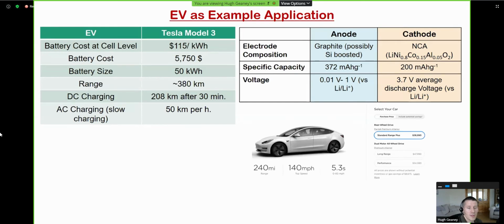If we're talking about just the graphite on its own, the capacity of graphite is about 372 milliamp hours per gram, which essentially is just a measure of how much lithium can be stored in the anode. And then the voltage window that it usually operates over is about 0.01 volts to 1 volt versus lithium. On the cathode side of things, we have the NCA in this case.